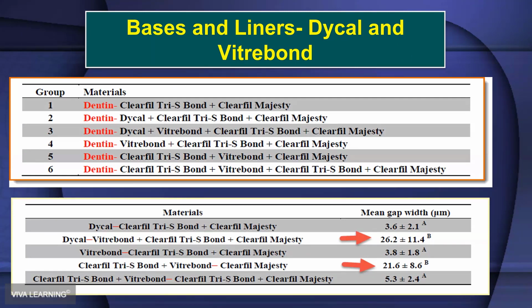The only one that didn't was group number 6, where they would have dentin, bonding agent, Vitribond, more bonding agent, and then Clearfil Majesty, the composite. And this is easily understood because Vitribond is, again, a resin modified glass ionomer, and so it has a lot of moisture. It has water in it. And composite is very hydrophobic, right? So you can't put composite directly on top of Vitribond because it's like putting oil-based paint on top of wet wood. It just doesn't work well. I mean, it may look like it's okay, but it really isn't.